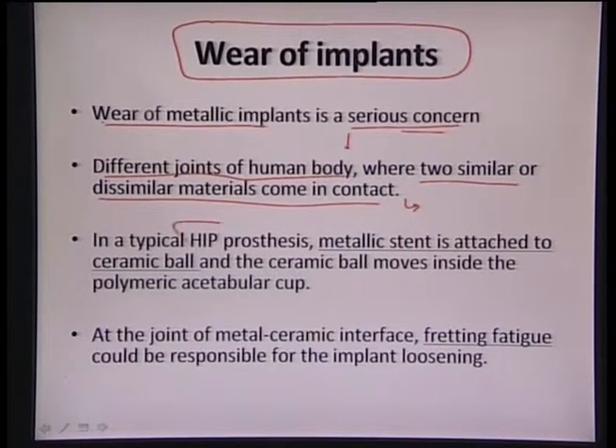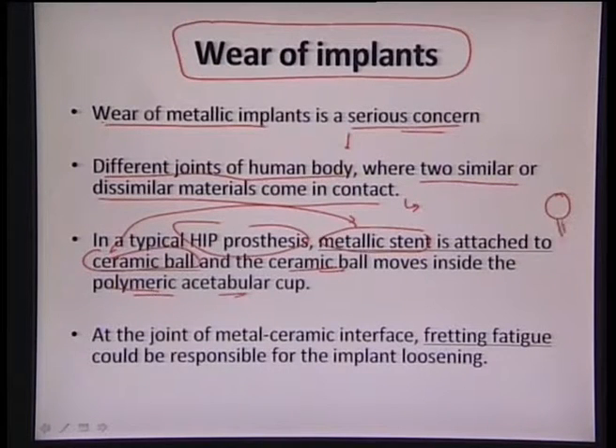Like in a typical hip prosthesis, a metallic stem is attached to a ceramic ball. Because of the interface between the ceramic ball and the metallic stem, there is some relative movement, and the ball moves either in the polymeric acetabular cup, or the ball is made of some material like stainless steel or titanium, and over that we have a polymeric liner or a ceramic liner. Between the metallic and ceramic interface, we can see much more fretting wear. That fretting wear can easily cause loosening of the implant.